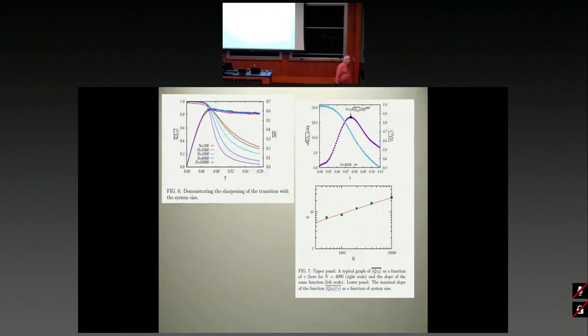I think the question is about the stress after the quench? Strain. After the last quench? Okay. All the application of the strain is quasi-static. I do a small step of strain, and I allow the system to energy minimize. It doesn't change the temperature. Temperature 0. I said all quench to temperature 0. This is a 0 temperature theory. And I'm going to say something about the finite temperature, but at this moment it's a 0 temperature theory. So as you see, this is becoming sharper and sharper. Now, I'm coming back to the comment that I said, that the yield is really stressed ergodization.